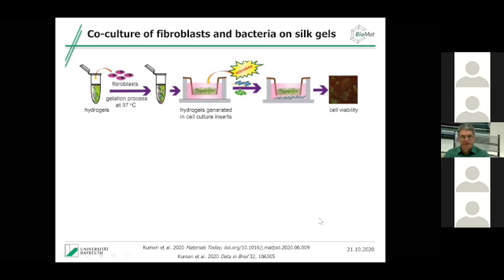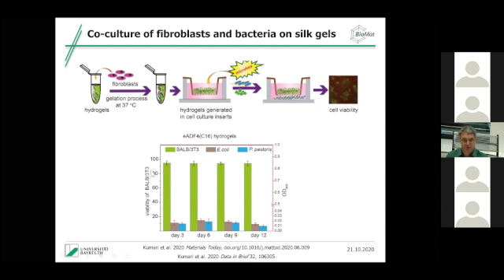So what does that mean? Well, this means now we could do co-culture experiments. So we could put fibroblasts and bacteria into the scaffold at the same time, then incubate that, and then check what happens to the fibroblasts and what happens to the bacteria. And the experiment is shown here. So the fibroblasts survive very nicely. We have about a 95% survival rate over 2 weeks. So the fibroblasts are fine. And again, we have an axis break here. And look at these numbers. There are undetectable amounts of bacteria and yeast. So even in the hydrogel, this system works.